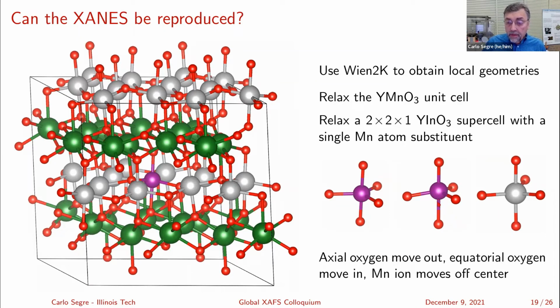And then the other thing is you can see that the manganese is now displaced toward one of the axial oxygen atoms. So it's closer to the one on top than it is to the one on the bottom. And there's a tilt to these oxygen atoms as well. That is, they're not in the same plane, or as close to the same plane, as they were before in the manganese or in the indium. And these are exactly the kinds of things that we see with the EXAFS. This is very similar to the kind of results that we get in the EXAFS study.